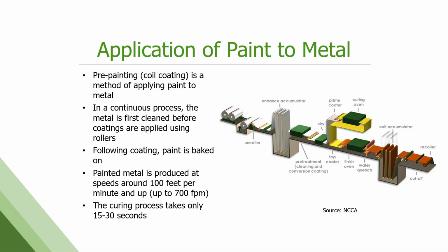It's quite large, quite dynamic. It's a continuous process. The metal is cleaned first, then the paints are applied and baked on. This process is typically anywhere from 100 to 700 feet per minute, so it's a quite fast process. And the curing, the drying of the paint usually only takes about 15 to 30 seconds. So very, very quick.